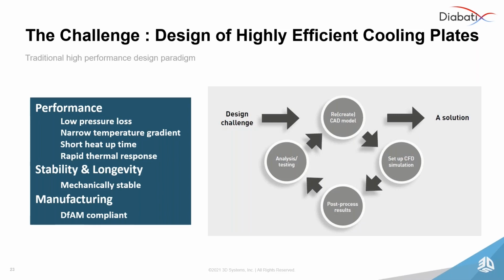to hit some specific requirements. And the requirements of a wafer table are going to be low pressure loss. So you want to make sure that you're not overcompensating or pushing too much fluid into the system and then losing that pressure with a super long line or inefficient cooling pattern. You also have a requirement for very low temperature gradient across the surface. And that's a measurement of how much you're allowed to fluctuate in your temperature across that surface.